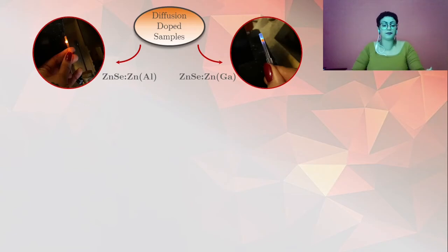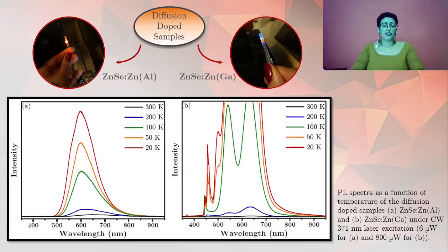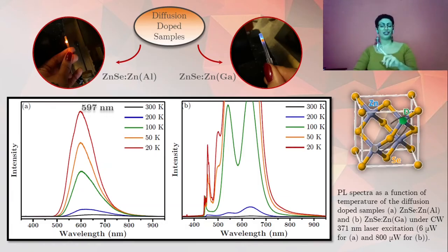From the PL measurements as a function of temperature for the aluminum-doped sample, it's possible to identify only a broad luminescence band, centered at 597 nanometers, that increases in intensity with the decrease of temperature. This band has already been associated in the literature as a result of high doping by diffusion with aluminum in zinc selenide. It is also related to radiative recombinations of complex defects involving zinc vacancies as acceptors and donor states introduced by the aluminum impurity.